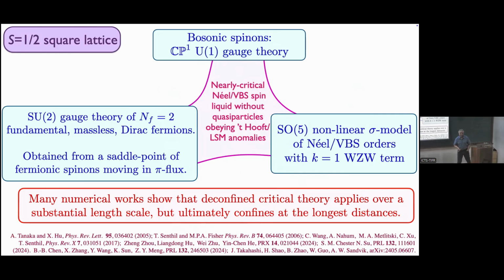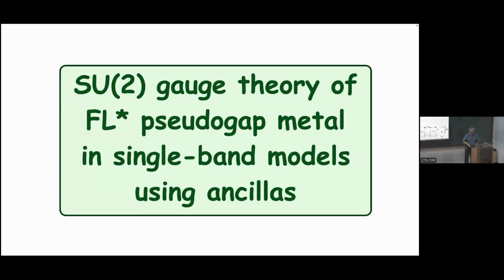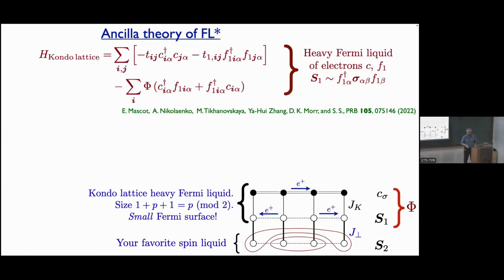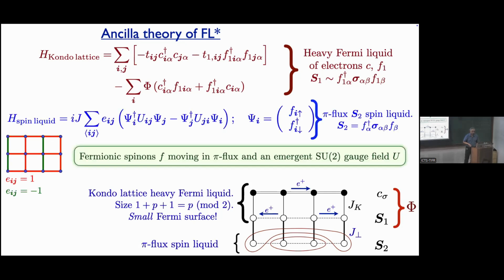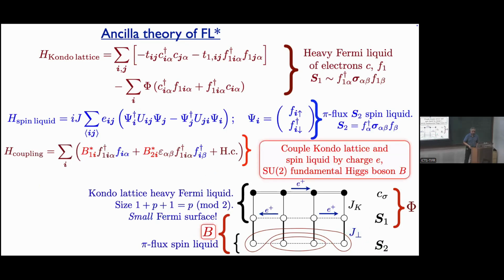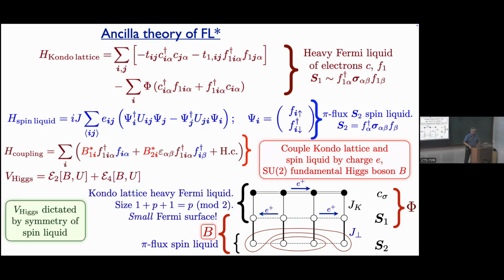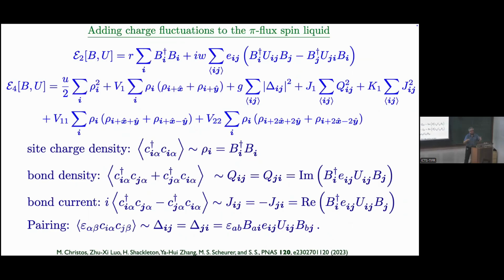I'm out of time. All right. So very quickly then, we start from the decoupled Kondo lattice and the spins. And now you take the particular Affleck-Marston spin liquid in the bottom layer. And then you introduce another Higgs boson, B, which couples the two layers together by factorizing the exchange coupling. And now it's all about this boson B. So we want to write down some effective energy, which you can just deduce by symmetry. So here's what it looks like.